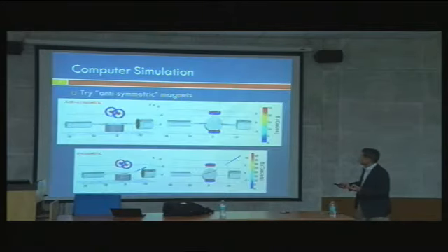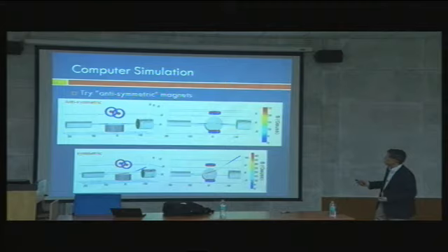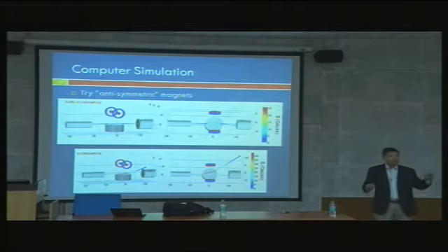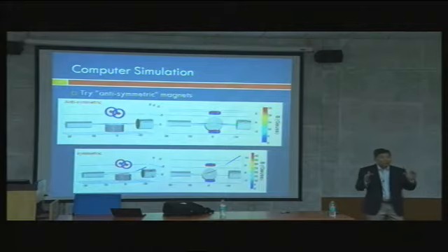Okay, so now we have two sputter guns face to face, and in that case, with the advantage of two sputter guns, you can use two different materials and different material systems. For example, I can use lanthanum nickelate, or you can use lanthanum manganate. That's what Jean-Marc Triscone's group published in a paper in Nature Materials, with two different material superlattices. But you can also use the same material from both, deposited without rotation. You get more uniformity over a large thin film area.